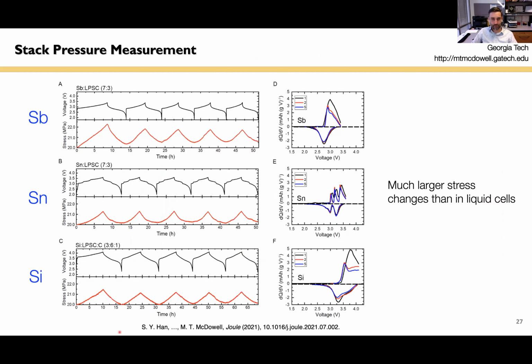And so here is a pretty extensive data set. What each one of these plots shows, on the top, the middle and the bottom, is the charge and discharge of a solid state cell. On the top, it's an antimony electrode at the anode. In the middle, it's a tin electrode. At the bottom, it's silicon. And so these are the voltage curves in black for each case. They all look different because you have different plateaus and everything. And then in red, you can see the stack pressure change, or the stress change. So each of these cells starts at 20 megapascals applied stack pressure.